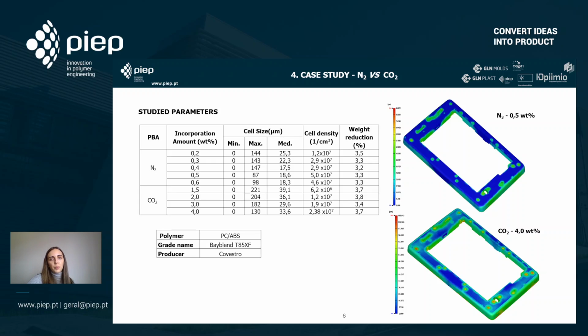So what we wanted to do was to analyze different amounts of incorporation of either N2 or CO2 and evaluate these results. The amount of incorporation of CO2 and N2 is very different because either gases have very different values of solubility in the polymer melt. In the case of CO2, it is much more soluble, and so to saturate the melt with the gas, you need a much higher quantity of CO2 than N2 for the same result.